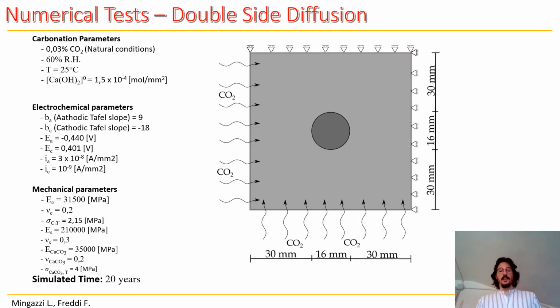The first numerical test we present is the double-side diffusion, in which we considered a square specimen with a 16 millimeter diameter bar placed in the center, with a flux of carbon dioxide coming from the left and bottom side at a natural concentration. The vertical displacements are blocked on the top side of the specimen, while the horizontal displacements are blocked on the right side of the specimen. The simulated time of this test is 20 years.